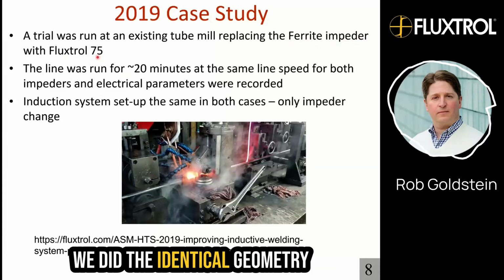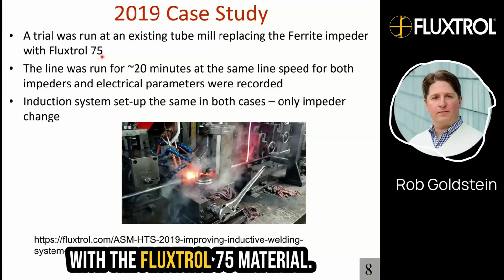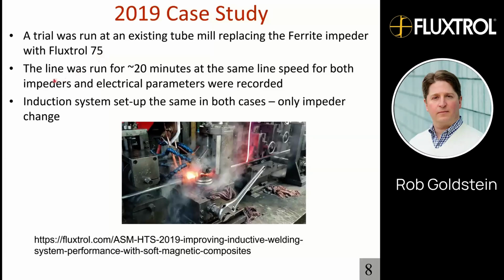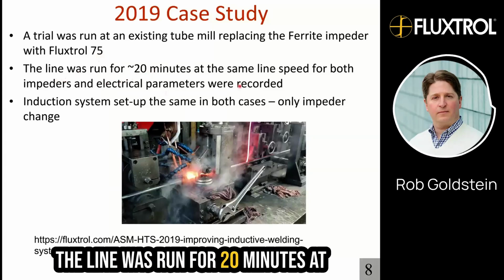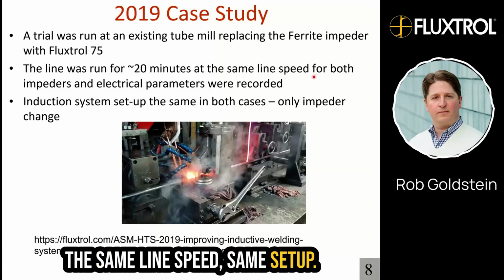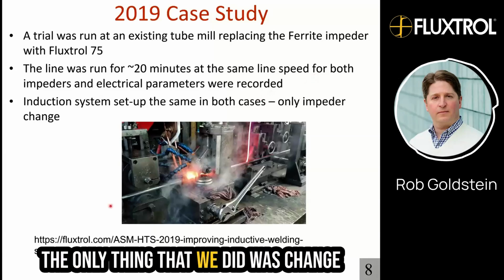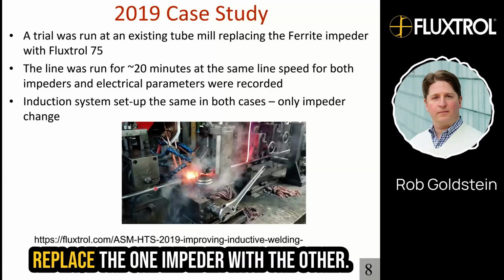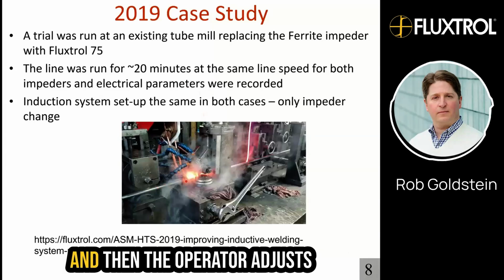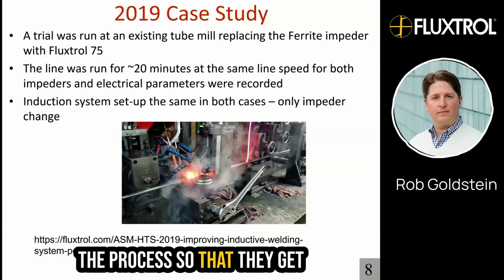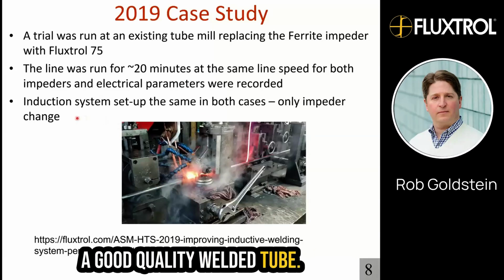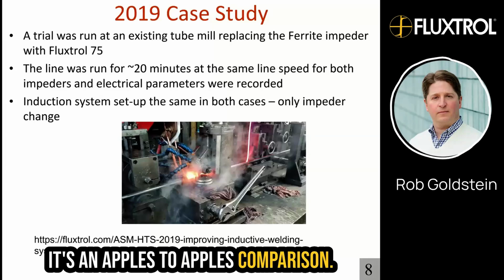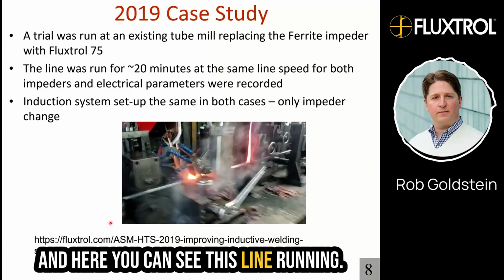We did the identical geometry with the Fluxtrol 75 material. The line was run for 20 minutes at the same line speed, same setup. The only thing that we did was replace one impeder with the other, and then the operator adjusts the process so that they get a good quality welded tube. It's an apples to apples comparison, and here you can see this line running.